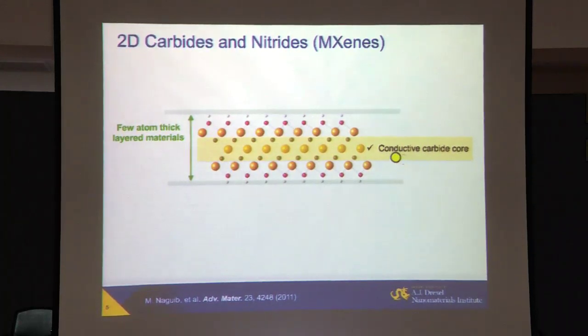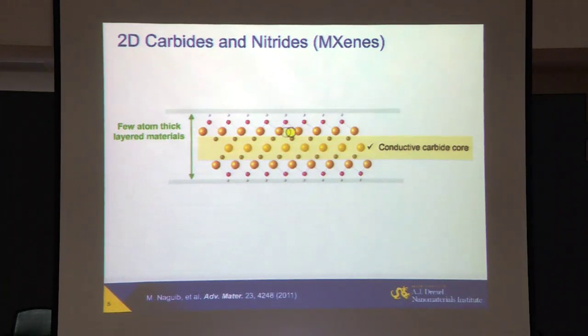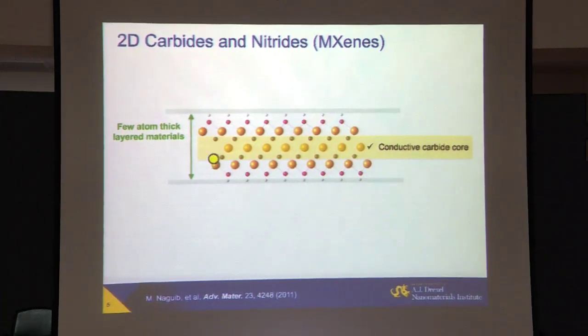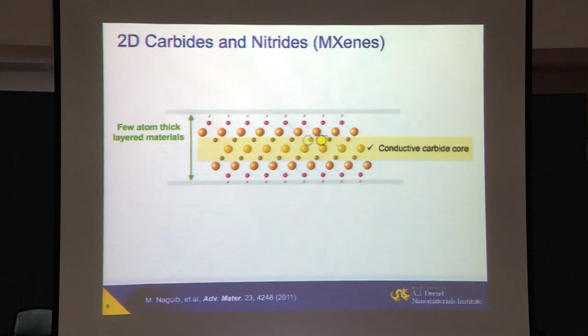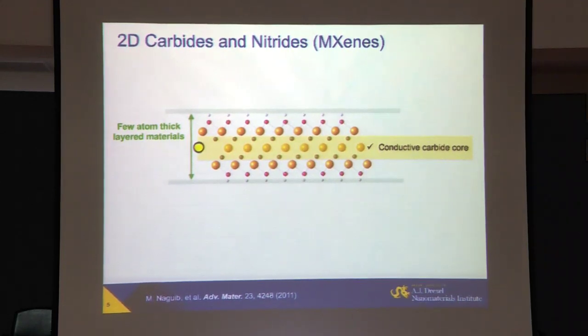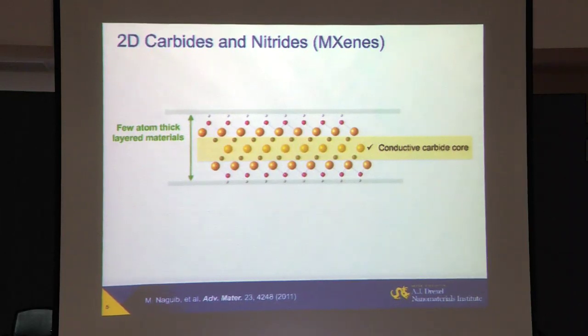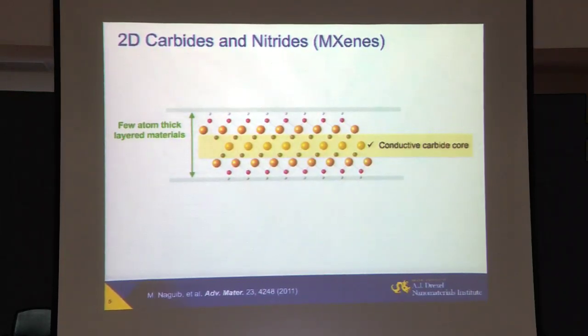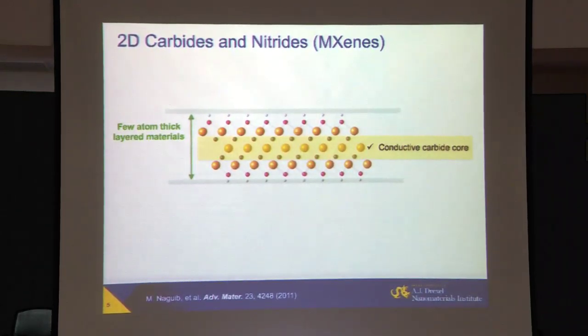They have conducting carbide cores. And actually, these large golden spheres are transition metal atoms I'm showing to you. The small dots in the middle, the black ones, are carbon or nitrogen. And I'm showing the surface termination by OH groups because we produce them by wet chemical synthesis here.